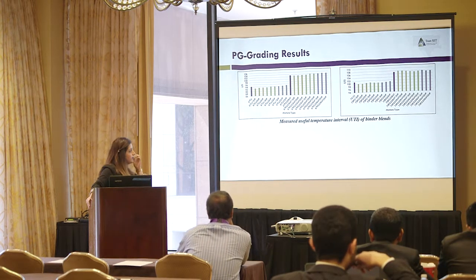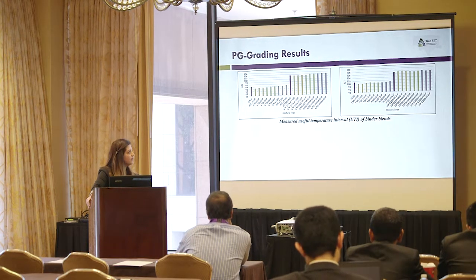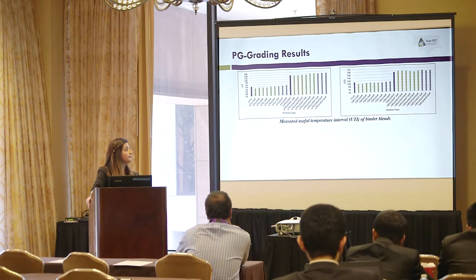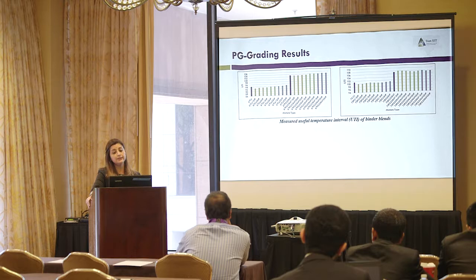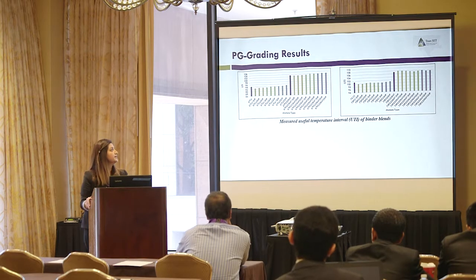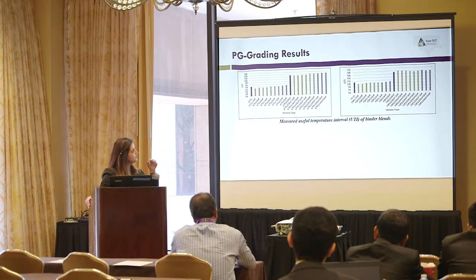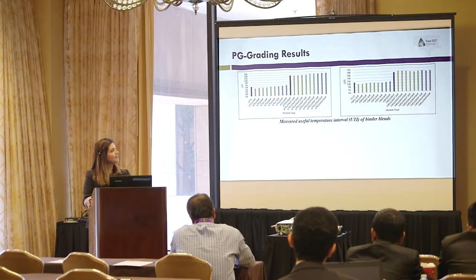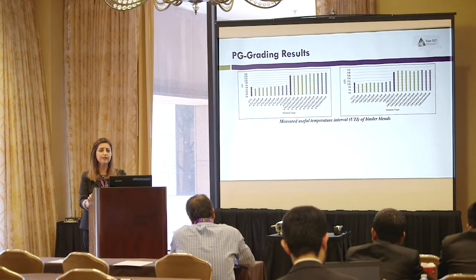Result from PG grading. In order to show the result from PG grading, we use the UTI, useful temperature interval. As you can see, addition of recycled material to the binder blend caused an increase in UTI of different blends, and addition of self-healing polymer with 1, 3, and 5% caused an increase in the UTI of different samples. This increase was further continued with the UV exposure. However, the change in high temperature grading of different binder blends wasn't significant enough to change the high grading of the samples.